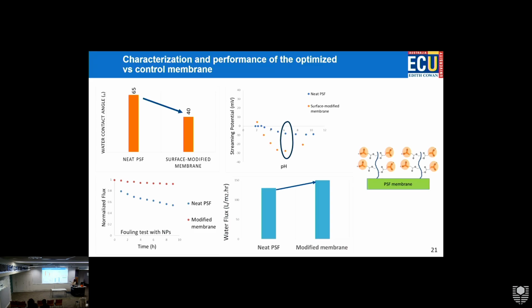So characterization and performance of the optimized versus control membranes in that test. Only the optimum sample is presented here. As I mentioned, we want the contact angle to be lower, which is indicative of a more hydrophilic surface, am I right? So with the surface modified membrane, we have a lower contact angle, so we have a higher affinity towards rejecting contaminants.